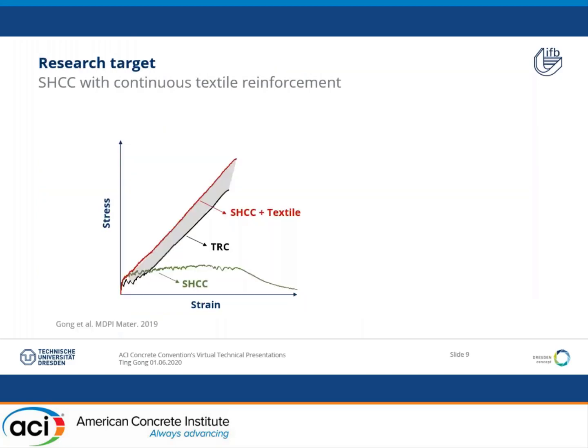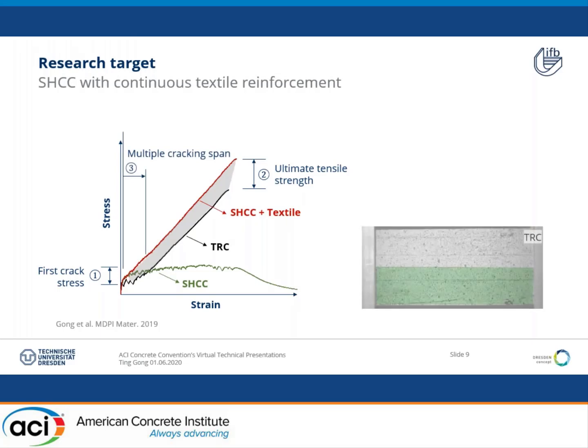As we can see from this schematic diagram, we expect an increase in the first crack stress, an increase in the ultimate tensile strength, and the subsequent high energy absorption. But the most interesting part here is that the multiple cracking span can be largely expanded. If we have a closer look at the video here, we can observe a very typical crack propagation sequence of TRC. First, the crack-free stage, followed by the formation of fine cracks due to the increase in the tensile stress. In the last stage, no new cracks will appear, but existing cracks will grow and become wider until the ultimate stress is reached.